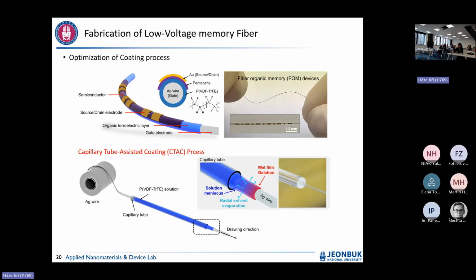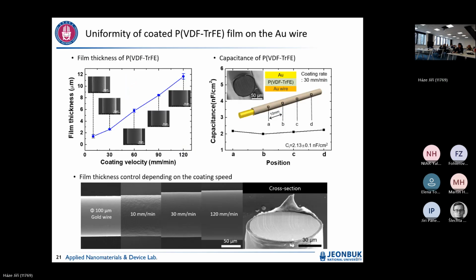So let's think about that. This fiber is really one-dimensional, right? So we can really get the core-shell structure. Then the uniformity is really nice. When this is a bare gold wire, depending on the pulling speed, you can control the thickness as well as the quality. Because we measure the capacitance at different sizes. So you can see here, the capacitance is almost the same. It means that the uniformity is okay.